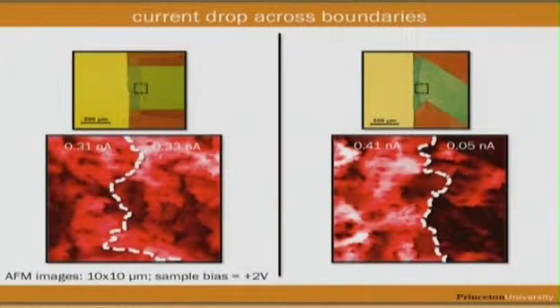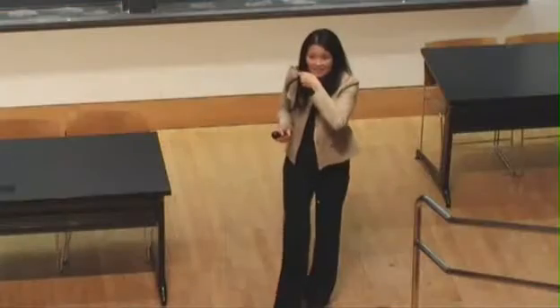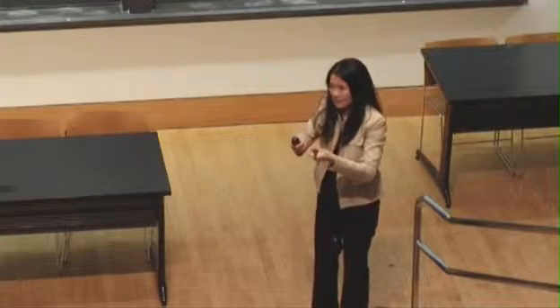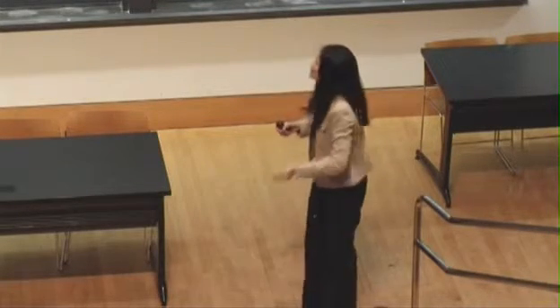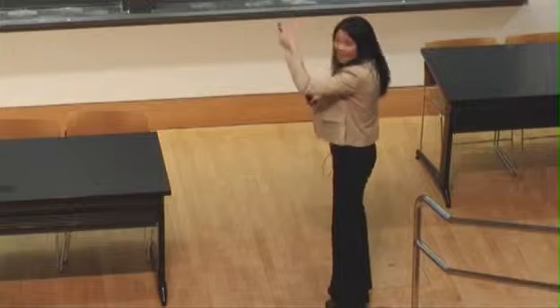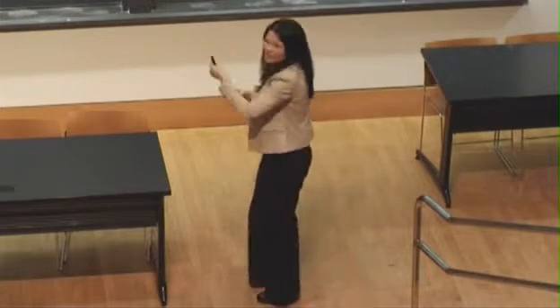And you can see that the current differences are small. But when you probe the current map across a high angle boundary, you can see that the current drop is actually pretty large. You can assume a model of resistors in series and back out the resistances. And it turns out that these kinds of boundaries are twice or more than twice as resistive as these kinds of boundaries. So that's telling us that if we want device uniformity, you don't ever just make one device. You make many, many devices over a large area. You want to try and avoid these kind of boundaries, but these kind of boundaries are OK, right?